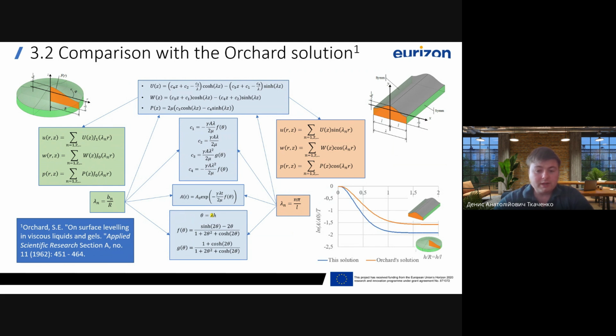Compared to the planar case described by Orchard, the axisymmetric formulation shows a faster smoothing rate due to the added circumferential curvature, which increases surface tension driving pressure.